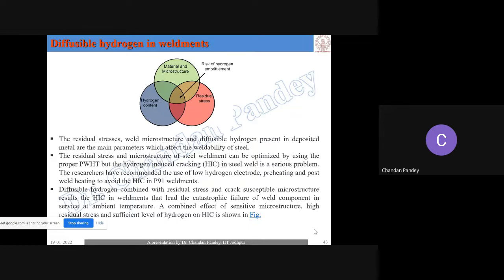Now, if diffusible hydrogen gets trapped in the region of your weld metal, it will move from one region to another, depending upon the temperature and service condition. When it moves from one location to another, it will create a cavity inside the region of your weld metal. Once a cavity is created, we can consider it like a stress concentration. From that point we can get crack initiation, and ultimately failure. That's why measurement of diffusible hydrogen content, and how we can minimize it, is very necessary in case of dissimilar joining. The crack failure associated with diffusible hydrogen is called hydrogen induced cracking.